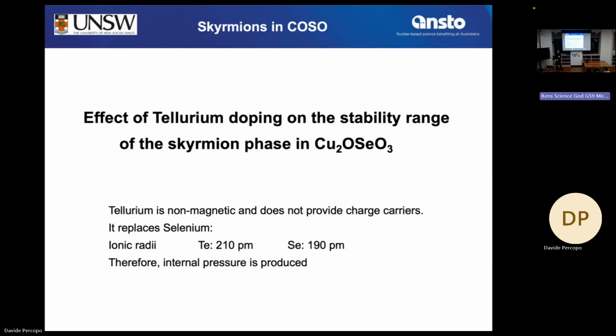Okay, very quickly, a short chapter here. Our material orders at about 60 Kelvin, which is miles away from industry applications. We need room temperature. So we tried to find a way how we can extend the skyrmion stability range, hopefully to high temperatures. So we did tellurium doping, which means we substituted the selenium with tellurium. Tellurium has a slightly larger atomic radius. So if you just consider atoms to be tennis balls, a larger radius means there's quite an internal pressure. And this internal pressure is huge because it's on the atomic scale. So simply spoken, tellurium doping means we applied internal pressure. So let's see what happens.